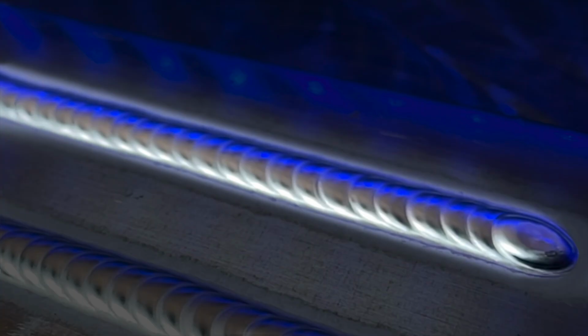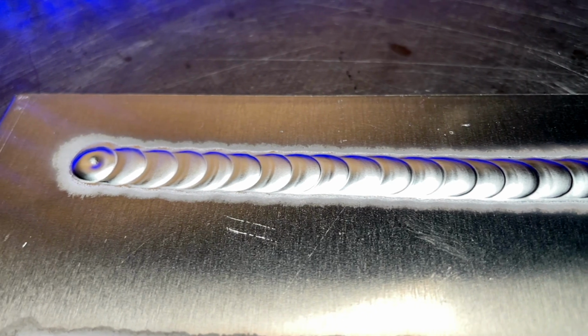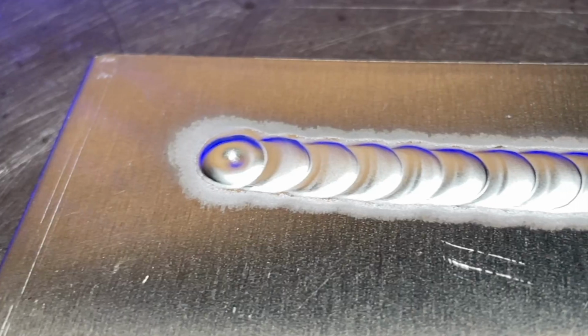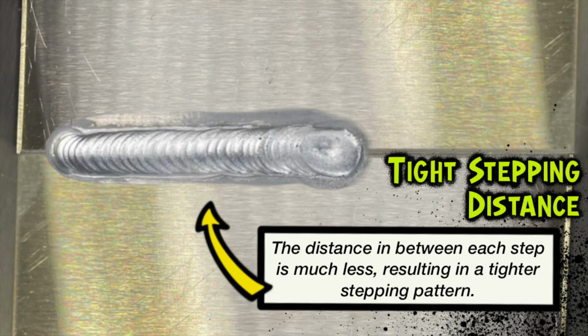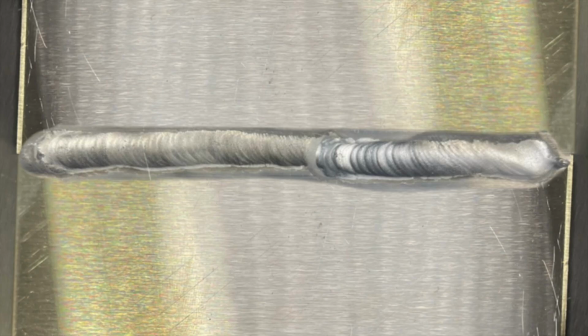No matter what distance of stepping you are using, your current puddle always wants to cover the center of the previous puddle. Sometimes stepping a little further apart can cause the filler material to fall a little bit flat, and when this happens, it can cause inadequate penetration to the base material. Sometimes when we really tighten up the stepping distance, this can actually decrease our travel speed, and when this happens, this can increase the overall heat input into your workpiece, resulting in overheating.